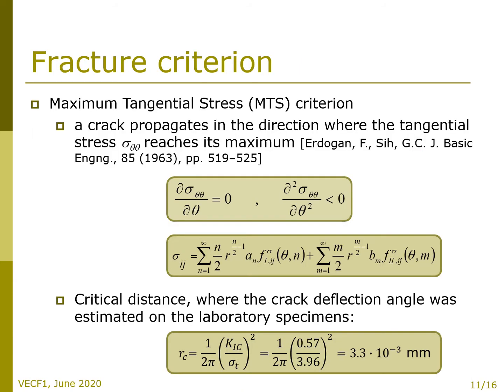When the coefficients of the higher order terms of the Williams expansion are known, an arbitrary stress tensor component around the crack tip can be approximated. And this is what is needed for application of the multi-parameter form of selected fracture criterion. In this work, the generalized MTS criterion was applied. It means that the direction where the tangential stress reached its maximum was searched.